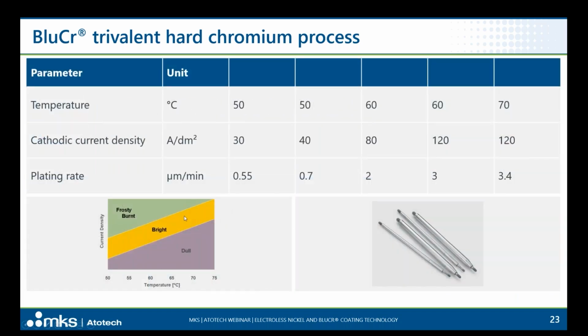Let's look at the parameters. So during plating, we have mainly two parameters we can play with to achieve different plating rate. So one of the biggest differences, let's say, for electrolytic hard chrome coating technology, if you compare to Electroless, is that the bath is very fast. So the plating rate is fast. And we can achieve plating rates starting from half of the micrometer per minute and end up with several micrometers per minute, which is comparable, for example, to existing Dynachrome technology, who is knowing about that. So this is our trivalent fast plating technology.